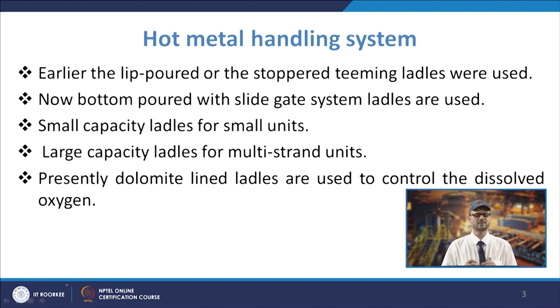Now, presently what we normally do is use these dolomite lined ladles to control the dissolved oxygen. What has been seen is that you may have the lining with dolomite, or with bauxite, you may have even the lining with silica. And it has been seen that the ppm of the oxygen observed in the case of dolomite lined ladles or even the bauxite lined ladles is lesser.